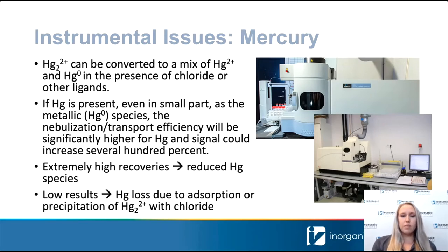Since mercury metal is volatile, you're going to have a much higher nebulization efficiency, and you're going to flood your plasma with that mercury species and get really, really high recoveries. So if you're seeing high recoveries of several 100% or even way more than you would expect to see, this is probably an indication that you have metallic mercury species in the solutions.